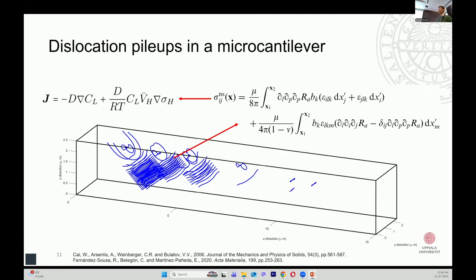Well, we can use this approach to check it. We simulated first dislocation dynamics and get this kind of a dislocation structure. And then, as mentioned, we can evaluate the dislocation stress field, and from the stress field, we can extract the hydrostatic stress field, as well as the gradient of the stress field. And then we apply this classical modified Fickian diffusion to simulate hydrogen redistribution. What is important is, in this process, we do not explicitly consider any trapping parameters like trap density, trap binding energy. We don't consider them.